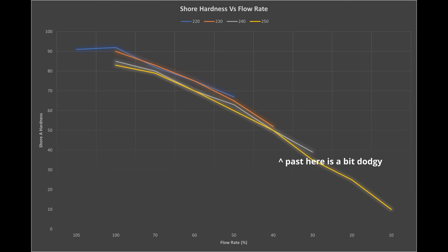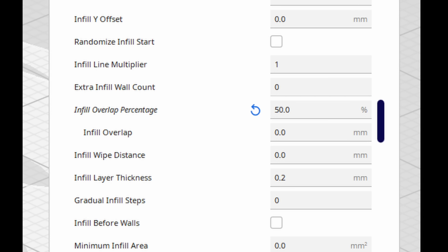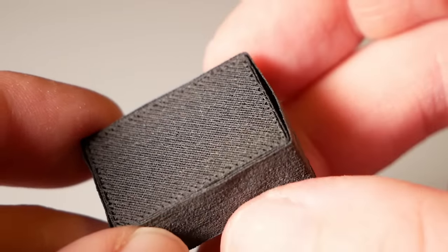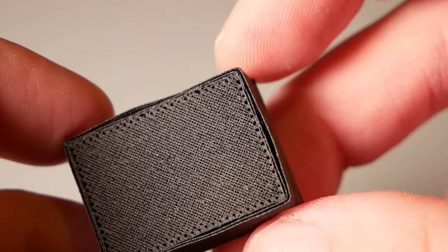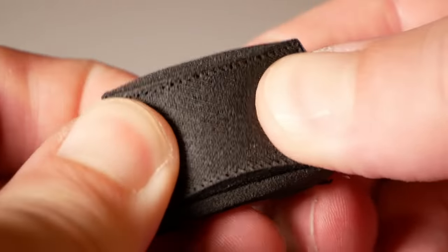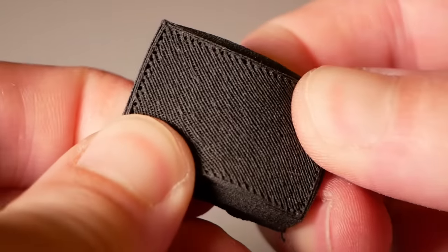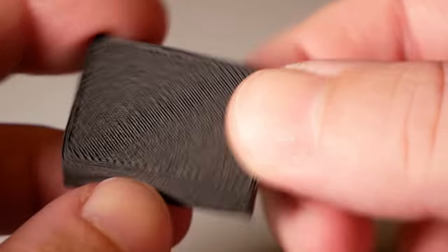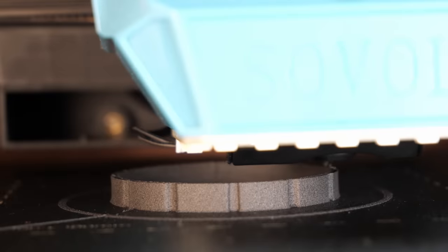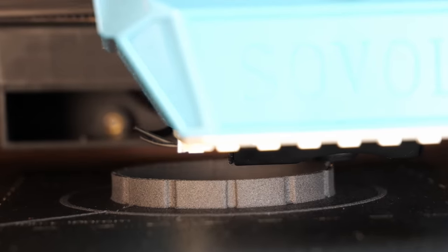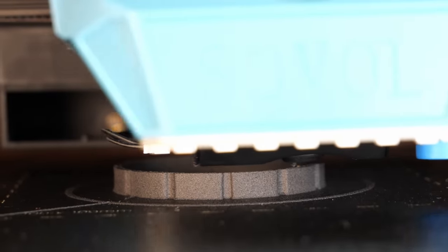There is a solution to this. You can use infill overlap in Cura here, this can be increased to compensate. If you're going to do this it's easier to go down to one outer wall so that you don't have to worry about the walls delaminating from each other. There are again ways to fix this, you can move the walls closer to each other. I don't have room in the margin of this video to explain all that and anyway you wouldn't really be doing this if you didn't want a softer part and a single wall will achieve a softer part.